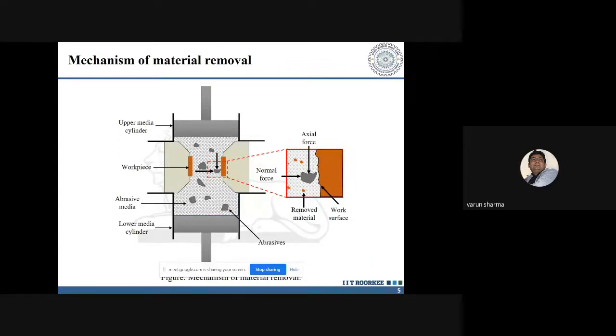So the idea was to change the trajectory of this particular abrasive particle. Now, when we used over here permanent magnet, I cannot change the magnetic field intensity. If I am changing it, I am going to invest into my setup. The other way was trying to develop an electromagnet because I can change the magnetic field intensity from 0.1 to 0.2 to 0.3 Tesla. If you go for a higher end, you can go for 0.5 Tesla kind of a magnetic field intensity over that particular case.